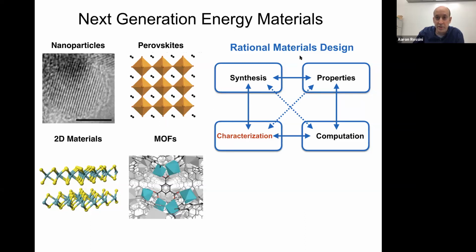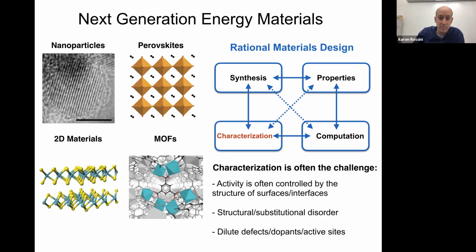So if we think about the typical design cycle that material scientists and chemists undergo when they're making these materials, they're going to synthesize something, measure properties, perhaps perform some calculation, and then characterize things and try to go through this rational design cycle. And I would often argue that characterization is the bottleneck here, because when we think about these materials, in many cases, the activity is going to be controlled by the structure of their surfaces or interfaces, and those are difficult to characterize. Oftentimes there's structural or substitutional disorder, and many times we have dilute defects or dopants or active sites. And by virtue of the fact that they're dilute, that makes them difficult to see or observe. So NMR is really an ideal technique that can address these challenges in characterization.